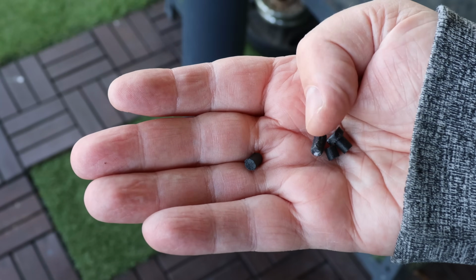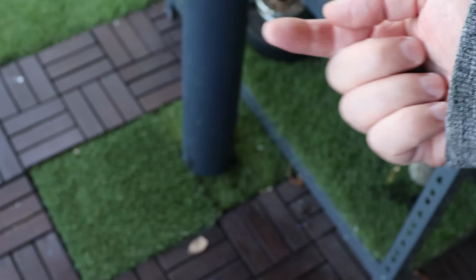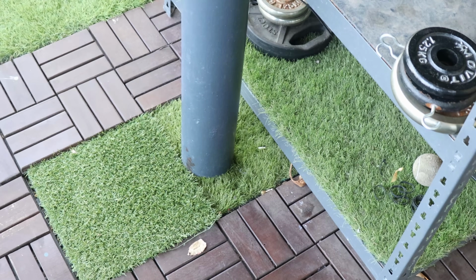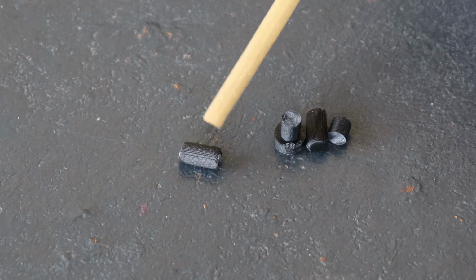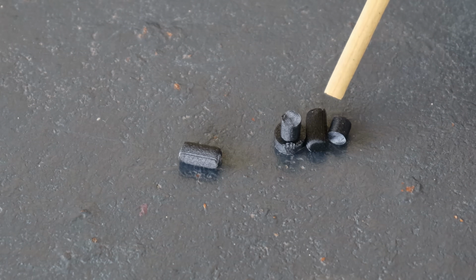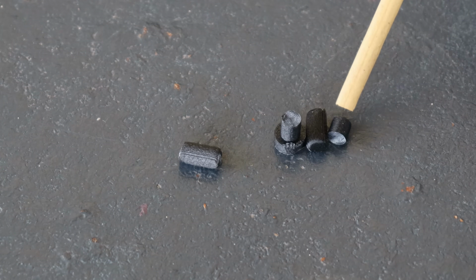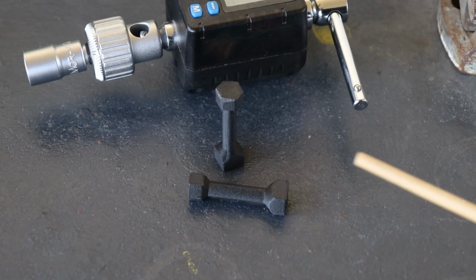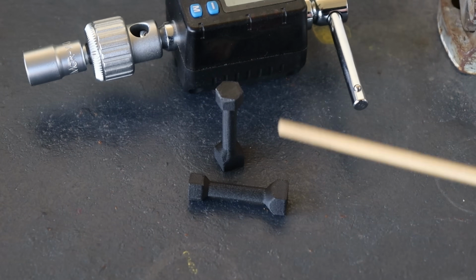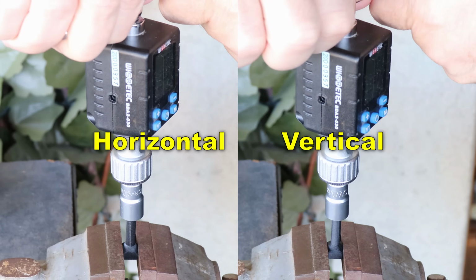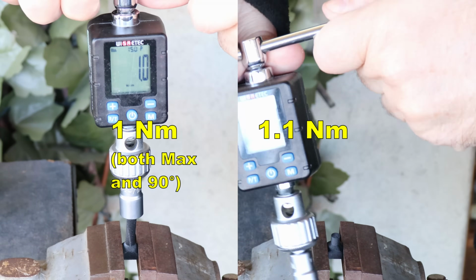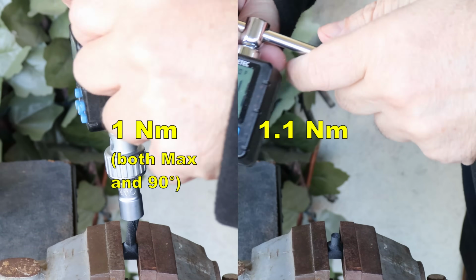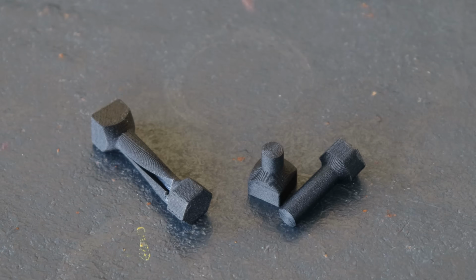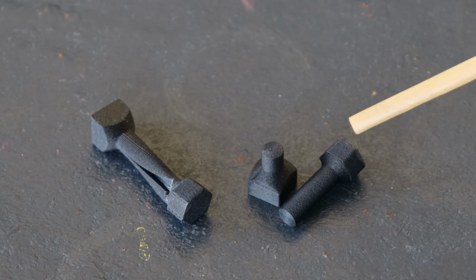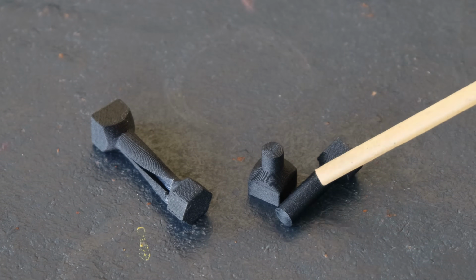They are sheared correctly in 3 pieces, only it is hard to find smaller black pieces on this surface. Printed horizontally very strong thanks to the carbon fibers, but printed vertically, well, we have the weakness of that layer adhesion. Torque or twist test with horizontally and vertically printed test objects with the same dimensions. Very often I can see similar numbers with horizontally and vertically printed test objects, only these usually break more suddenly.